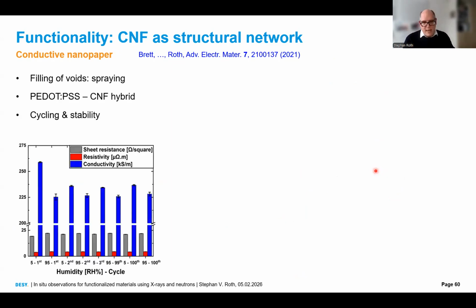You can do this in the lab. PEDOT:PSS is semiconducting. In the lab, you can do 100 humidity cycles, up 95%, down 5%, and so on. And I want to take a look with you first at the blue lines. Here you see the first cycle at 5%. We have a high conductivity, then we increase humidity, the conductivity goes down. Then we reduce relative humidity, conductivity goes up. Then we increase humidity, goes down, decrease, up, and so on. You can do it 100 times.